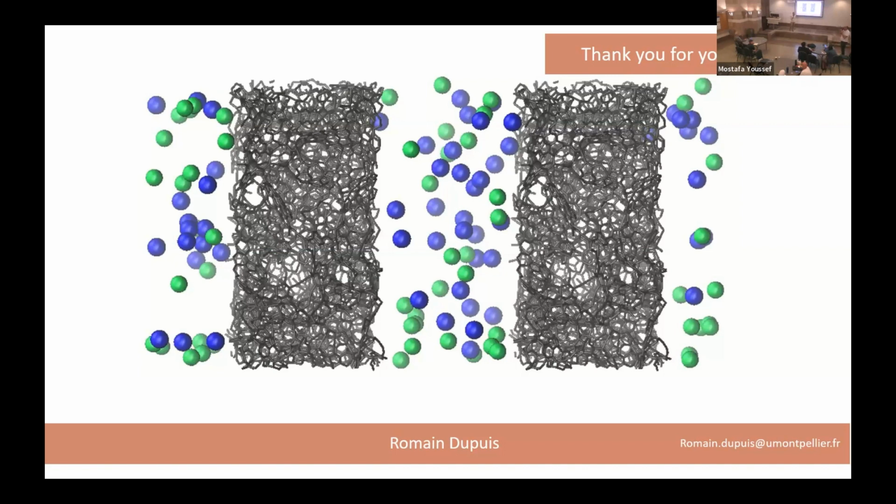But you do have a double layer of ions on the outside. So you have some ions getting in the pores, but most of them are on the outside. You have a double layer, like usual. And when you calculate the Debye length, it comes to the 2-3 angstrom that you would expect with this kind of ion concentration. The separation is around 30 angstroms, something like this, 30, 40. 40 angstrom, yeah, 4 nanometers. I think it's important to try different spacing, also for looking at confinement effects maybe. Yeah, could be nice.